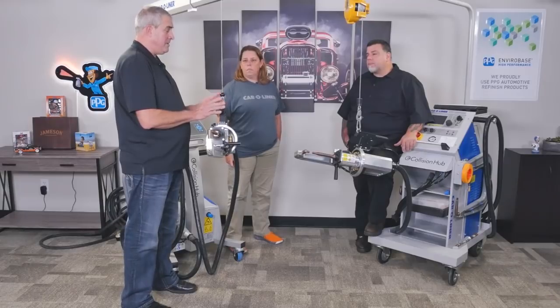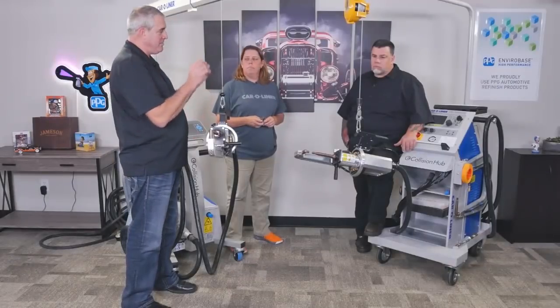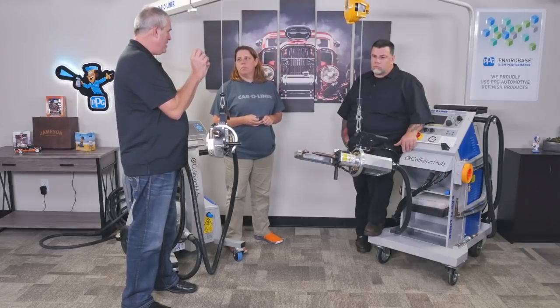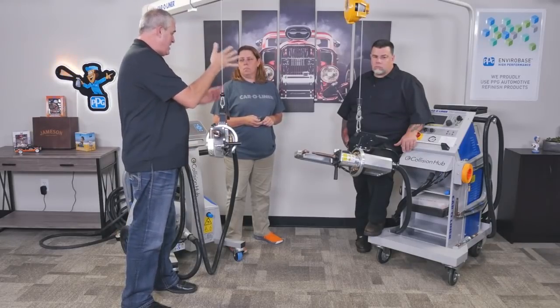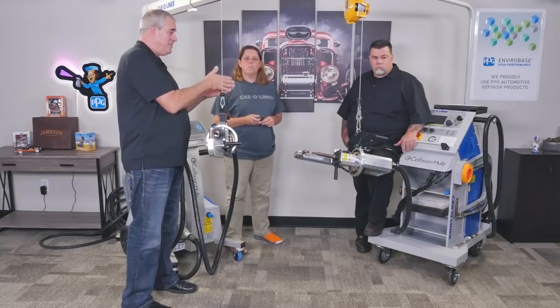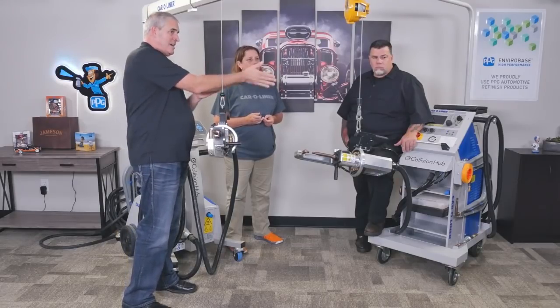And that's a big issue, because you might get a listing saying, okay, we did 43 welds, here's the thickness, and here's the amperage that went through it. But what was the tip mushrooming, or what was the tip? Did you prep the panels correctly? And did we actually have the tips? Because if the tip's a little wider, obviously it can get the same amperage and have a weaker weld. So there's still that whole aspect of the human side, not just the computer.